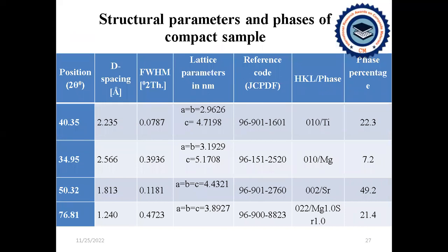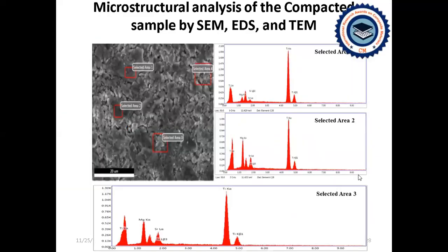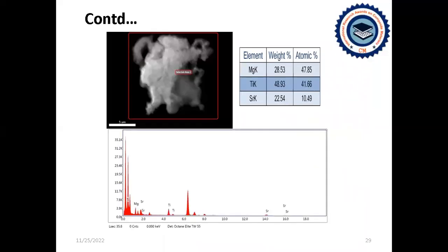This table represents the structural parameters and phases of the consolidated sample, and we have the HKL factors along with the phase percentages. This microstructural analysis of the compacted sample by SEM with EDS represents the elemental composition that is similar to the elements present in the ball milled sample.